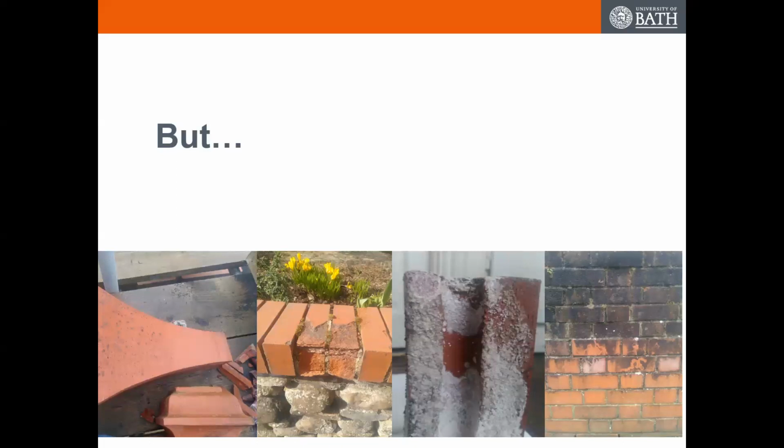That picture on the far left is from a different site. It's not going to be mentioned again tonight. But what happened there was that it was a fairly new piece of terracotta, a nice finial up on the roof. It had been put in in the 80s, using a 1980s sort of chemical epoxy. The chemical epoxies are very thick, and that terracotta was very, very well vitrified. It had almost no porosity, and there was almost no suction. When you're building a wall with bricks, you're relying on suction to glue the bricks and the mortar together. In this case, that finial had sat up there on top of that epoxy mortar under its own self-weight for about 20, 30 years until it blew off. We went up and checked all the other ones on that building, and they were all loose. They were just sitting there. So some porosity is useful. It's necessary.